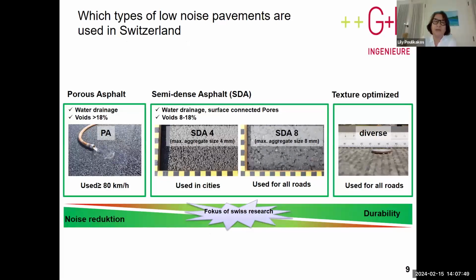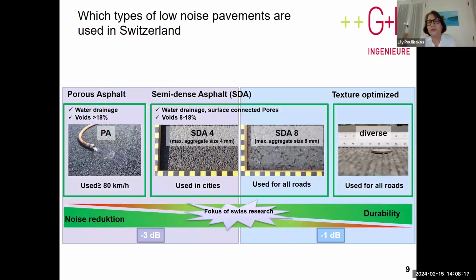Well, on the one hand, there's porous asphalt that has high air voids, and there's semi-dense asphalt with a little less voids, and then also the texture can be optimized. But as we reduce the noise, we also reduce the durability. So porous asphalt also has lower durability than the other options. So the different options also have different capabilities in terms of reducing the noise.